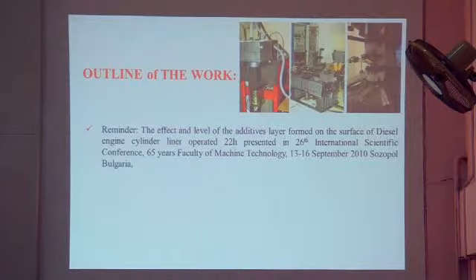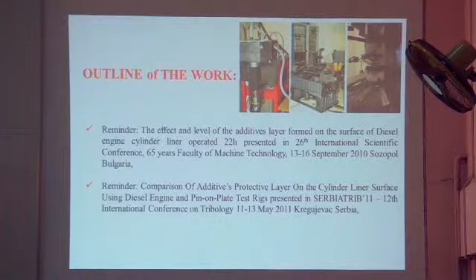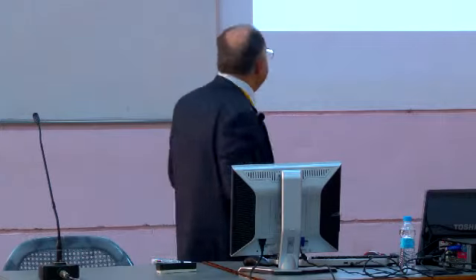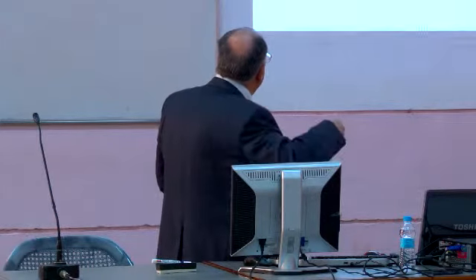But as we found the protective layer on the surface, since I'm in the automotive division, I was very interested to see how those layers formed on the cylinder liner in an internal combustion engine. So we did more experiments and detected those layers, and we also compared the cylinder liner with plates from the test rig at another conference.